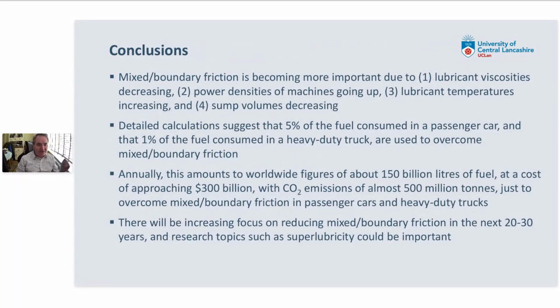So I've just about finished, hopefully just about on time. Hopefully I've convinced you that mixed and boundary friction is becoming more important because lubricant viscosity is going down. In addition, power densities of machines are going up. Lubricant temperatures tend to be increasing and sump volumes are decreasing. We've done some detailed calculations for passenger cars and trucks and found that about 5% of the total fuel used in a passenger car and 1% of the total fuel used in a heavy-duty truck are used to overcome mixed and boundary friction. And these costs, just the energy costs, I've not talked about the cost due to wear or replacement parts, simply the energy costs amount to enormous figures. So for passenger cars and heavy-duty trucks, we've estimated about 150 billion litres of fuel are used to overcome mixed and boundary friction at a cost approaching $300 billion, and CO2 emissions of almost 500 million tonnes.